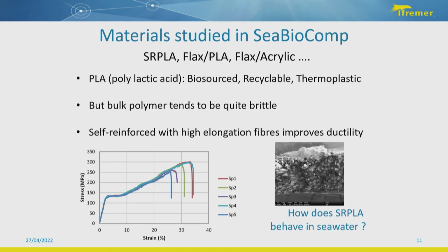So here are the materials that have been tested, and they have been well presented before, so I won't go back over this. But if we take one of the examples that has been presented before, it's the self-reinforced PLA. PLA is a really good candidate when we are talking about bio-based material, because it's bio-based first, it's recyclable, but one of the problems is that the bulk polymer tends to be brittle, and this can be a big issue for marine structures. So one of the ideas was to do self-reinforced PLA and to use the properties of high elongation of the fibers in order to improve ductility.